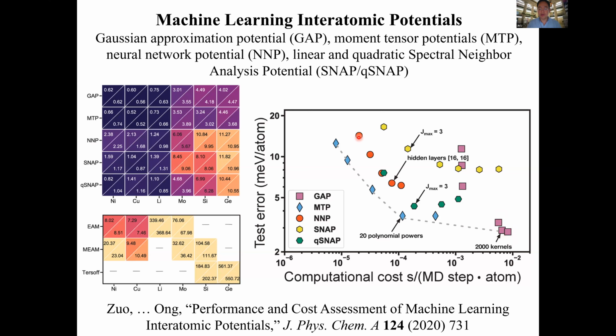And then the neural network potential is these red circles, and the SNAP, which is spectral neighbor analysis potential, are these yellow circles, and the qSNAP are these green circles. But in a plot of the computational cost and error, the Pareto front is actually this moment tensor potential, the MTP potential. And this is a comparison with well-known potentials: embedded atom potential, modified embedded atom potential, the Tersoff potential for pure nickel, copper, lithium, molybdenum, silicon, germanium.